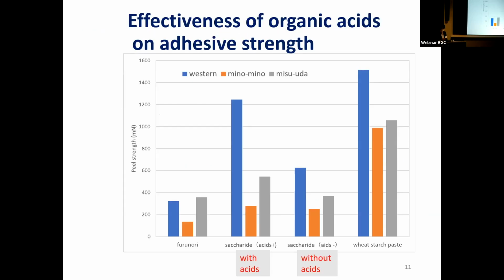however, was that the samples washed in water with organic acids showed stronger adhesiveness than those without. The results suggested that adding organic acids exerts a positive effect on adhesive strength. This is because furunori is always applied to backing paper that contains alkaline minerals, and thus the organic acids increased hydrogen bonding. The acidity of furunori thus positively affects adhesive strength, supporting furunori adhesiveness, which otherwise demonstrates weak adhesiveness, enabling its repeatability.